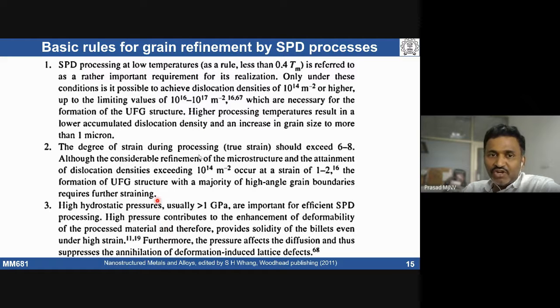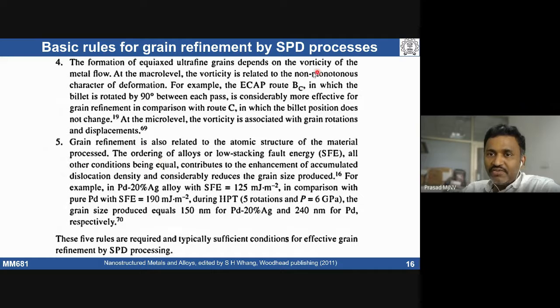The second one: we have to apply a very large amount of strain to get a homogenized fine grain size. Third, there should be some hydrostatic component. If you want grain refinement, the method should induce some hydrostatic component. The fourth one, the stacking fault energy plays a role. Depending on stacking fault energy, the cell size is going to be different, and accordingly we see a difference in the grain refinement. The fifth one is vorticity. We already discussed that we have to induce a vorticity of the metal flow.